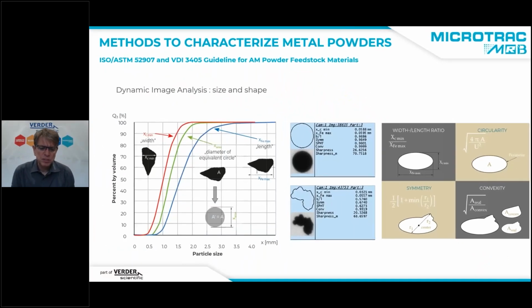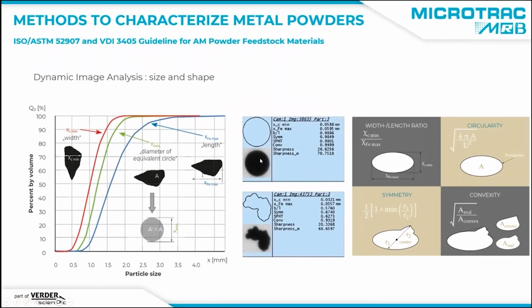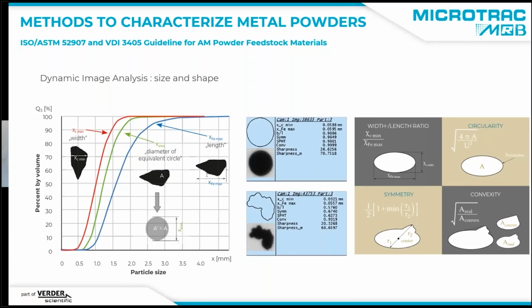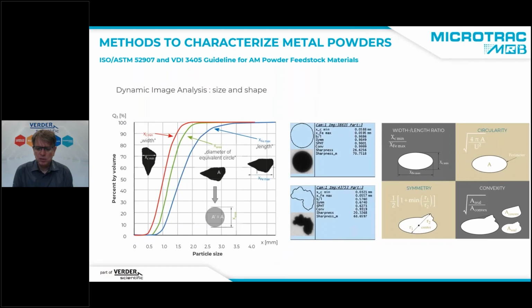This way we can measure the size of the particles. For example, we can measure the thickness of the particles or the length of the particles. Of course, if we have nice particles like the round particle here in the middle, then width and length are the same. But if we have irregular shaped particles like the particle on the bottom, then we get different values for length and width, and both numbers are interesting to get because they tell us if the material is nice and round, is homogeneous, it will be nicely flowing, or it will be a particle that creates problems when we create our layer in the printer.